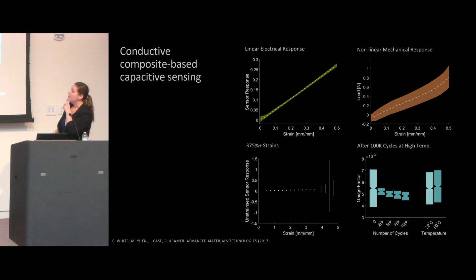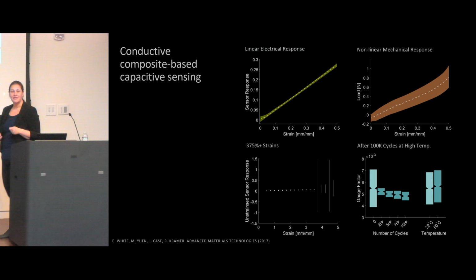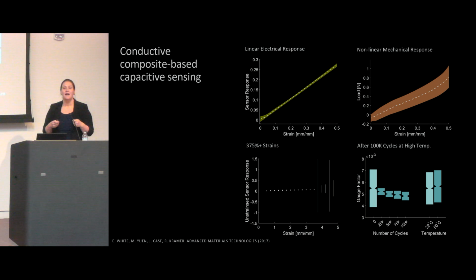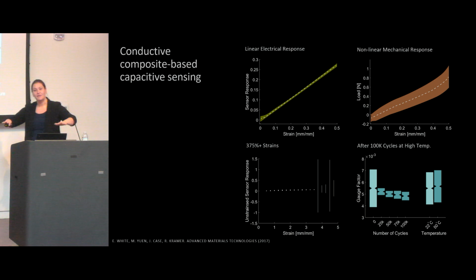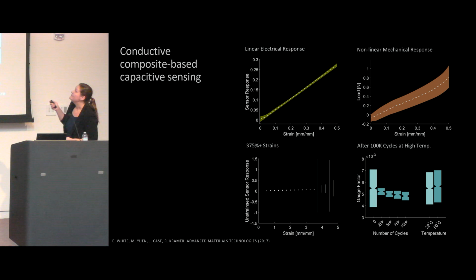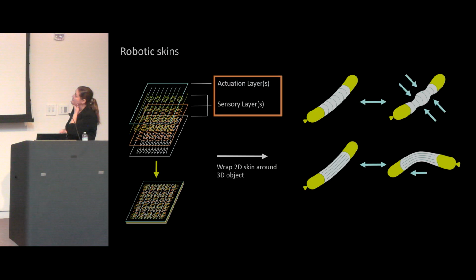So I will say before moving on that we have developed these sensors quite a bit further since this initial design. In addition to the graphite flakes, we've added liquid metal particulates. So we've made it a multi-phase composite. And this actually evens out the thermal conductivity throughout the electrode. The electrical conductivity and the percolation is much more uniform throughout the electrode. And so this has increased our linearity of response, especially at very high strains, quite a bit. So that's just some more recent work that we've been doing with this.